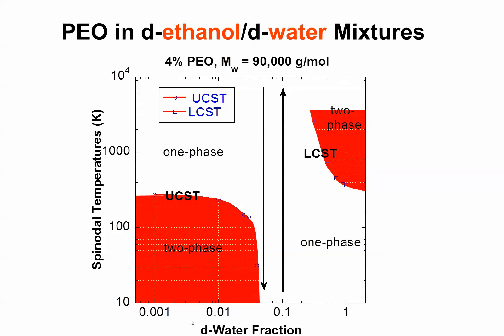And we figure out the phase diagram precisely. You start adding more and more water. So in pure ethanol, UCST, phase boundary is here. You add more and more water, it becomes LCST. And in between, we discovered a perfectly mixed region, window here, where there are no composition fluctuations whatsoever, going to very high temperature and low temperature, perfectly mixed. So this is co-solvation.